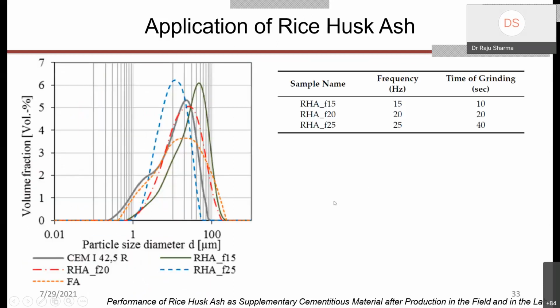And when you go for grinding of the RHA to improve the packing behavior, right? So F15, F20, F25 are the different frequencies and times of grinding. In that way, you can see the volume fraction and the density of the particles shifted towards the finer size. So you can see that RHA F25, frequency 25, gives you the maximum density at approximately 10 micrometers. And you can see the peaks are shifted towards the finer particle size.